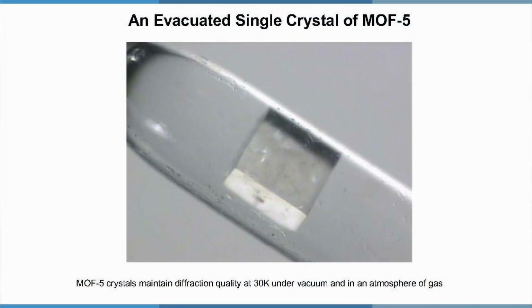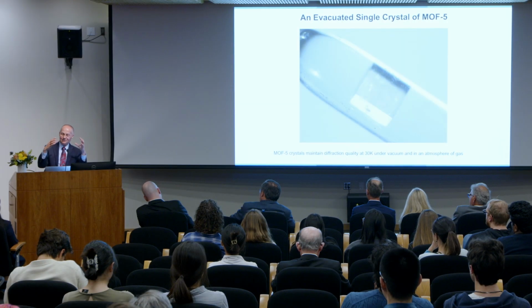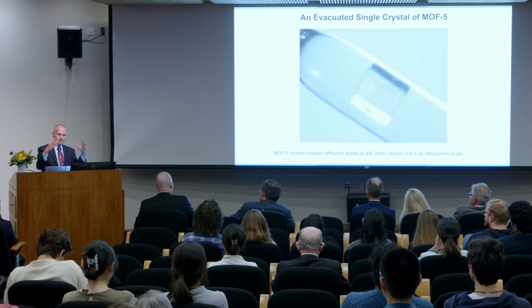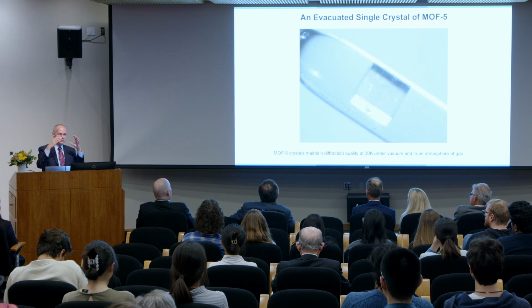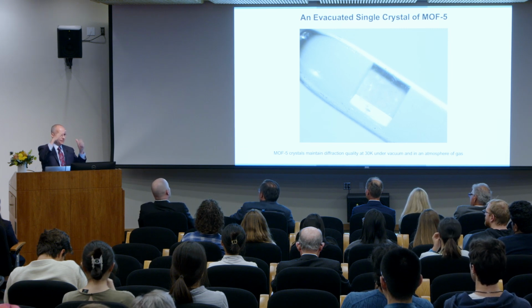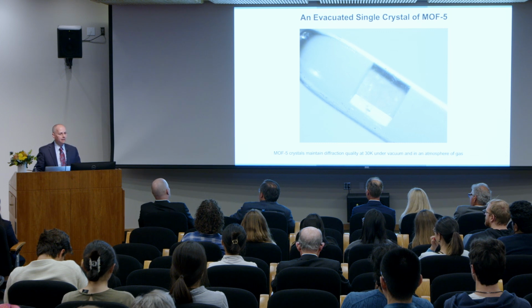We did an impossible experiment, and that was to take a crystal of that structure I just showed you to really characterize that it's truly porous. Because once you have a porous material, if there is no stuffing inside, nature abhors vacuum. If I take that stuffing out, now I have vacuum inside the crystal. So we wanted to prove that, in fact, when there was nothing in the pores, that the structure still is maintained.